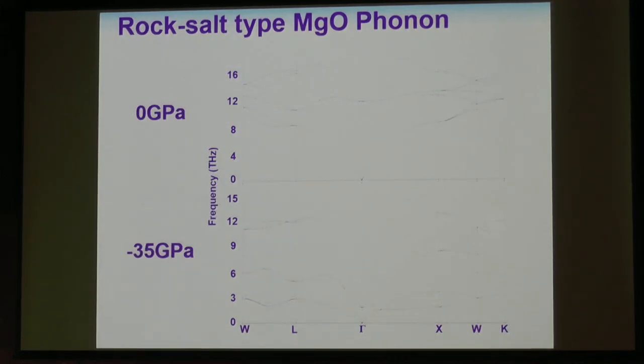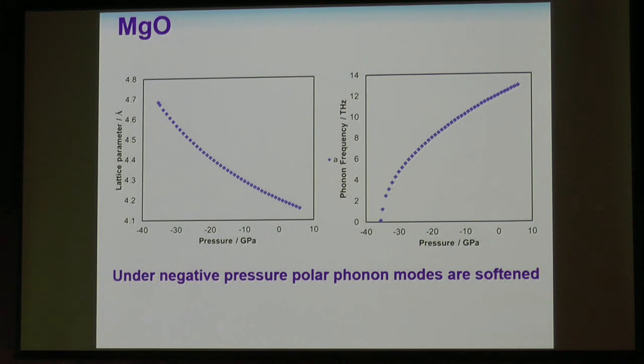It's very difficult to see, but this is the calculated result for the phonon dispersion curve for MgO at zero pressure. The polar mode, as shown here, is hard to see, but applying negative pressure, this polar mode goes down. So we can tune the soft mode using applied pressure. This is the calculation result. If we apply negative pressure, the phonon frequency goes down beautifully and the lattice parameter goes up. About 10% lattice expansion was found.